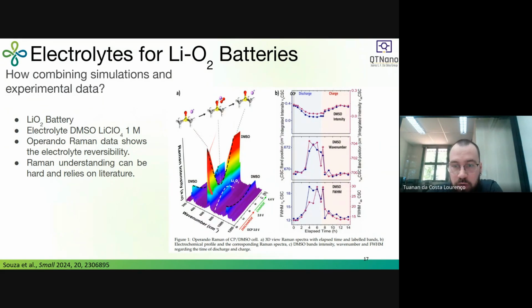So if we look here to this figure on the right, you can see that when they discharge the battery, there is a decrease in this peak. So this is the Raman spectroscopy. And when they charge the battery, there is an increase in the peak. And this also happens for other peaks, other bands here. So that means that from this data, we can understand that we have some kind of reversibility in the electrolyte, in which when we discharge and charge the battery, we are still keeping the integrity of the electrolyte.